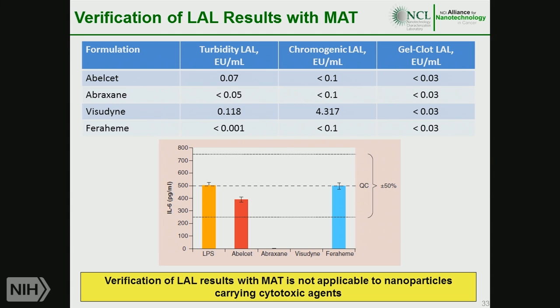This test is conducted in monocytes, and we are looking at the induction of the pyrogenic cytokines, TNF, or interleukin-1 and interleukin-6. Here you also see different commercial formulations of nanoparticles, say Abelcet, Abraxane, Visudyne, and Feraheme. And you see that for some of them, like for Abraxane, there is consistent data between different LAL formats: turbidity, chromogenic, and gel clot. But for some formulations, like for Visudyne, the result is inconsistent. And depending on which assay you use, you may either overdose endotoxin or be safe.